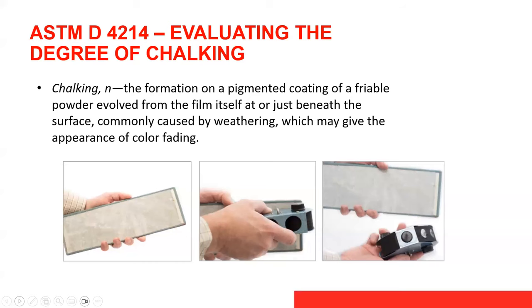We've talked a lot about gloss loss, and really what we're talking about is the film being degraded by weathering, particularly UV exposure. And that translates to something that we call chalking. Chalking can be evaluated. It's a visual standard. It's ASTM D4214. It's the degree of chalking.